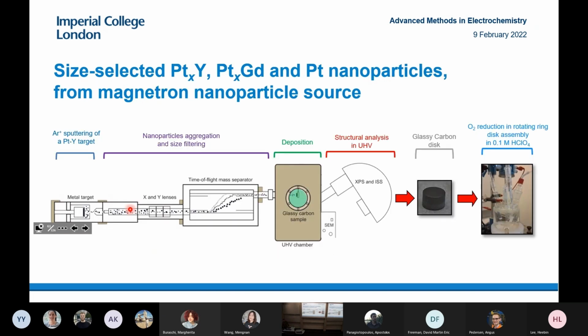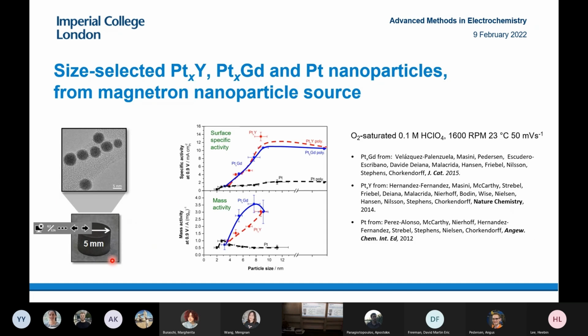We had a very elaborate tool for doing this. And then we tested the activity of these nanoparticles. So this is a surface-specific activity as a function of particle size. This is a bulk surface, and this is nanoparticles. We can see this is for platinum, and here's for platinum gadolinium, platinum yttrium. As we go to larger nanoparticles, we start to see significant improvements in activity, but not for the smaller particles. And we see up to about 3 or 4 times improvement, especially for platinum gadolinium nanoparticles.